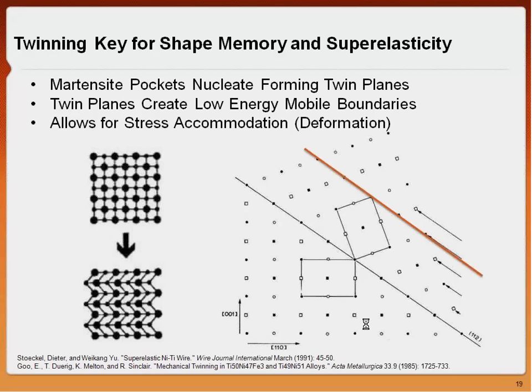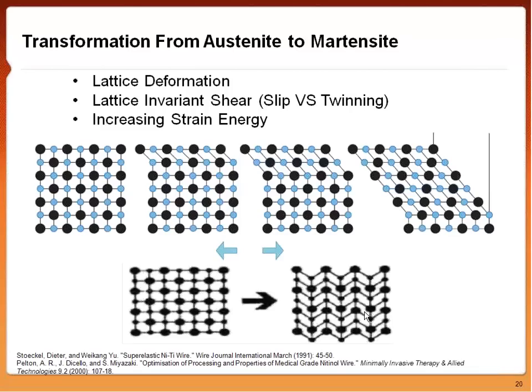So we can change nitinol simply by changing its temperature. And the thing we look into is that the bulk material doesn't actually change in front of us. When we put it in a cold solution, it doesn't bend. It stays that same raw piece of metal. And that happens because of two mechanisms: lattice deformation and lattice invariant shear.